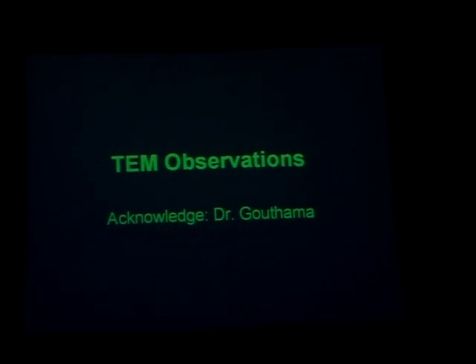Look at the surface. Phosphorus also is getting removed from the near surface region because it's going to the protective passive film most likely. Very interesting. TEM observation, same material. You can see I do notice some kind of segregation at the grain boundary. And also I found some phosphide precipitation in the material.